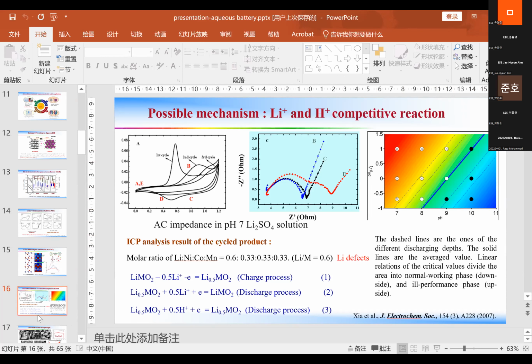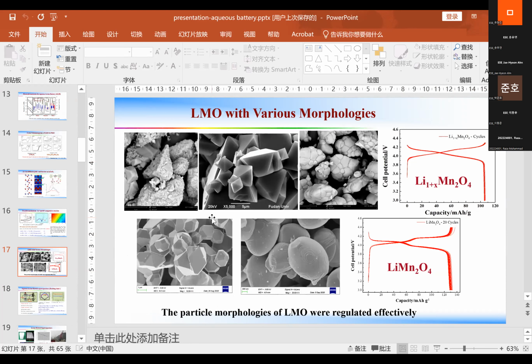So we chose the spinel, because for the layer compound electrode materials, like the layer structure NMC or lithium cobalt oxide, it's impossible to apply them in the aqueous electrolytes. So we choose the spinels. With spinels we can develop different morphologies, and very recently we developed spherical spinels. And for the cycling stability, we can control the lithium contents to adjust the cycling stability and the capacity. For the lithium-rich compounds, we normally have very good cycling stability, and for just LiMn2O4, we can get a capacity as high as 130 milliampere hours per gram. So this depends on what you want.